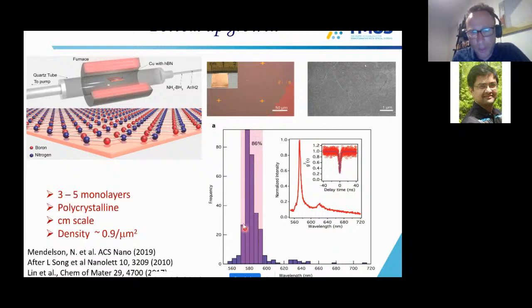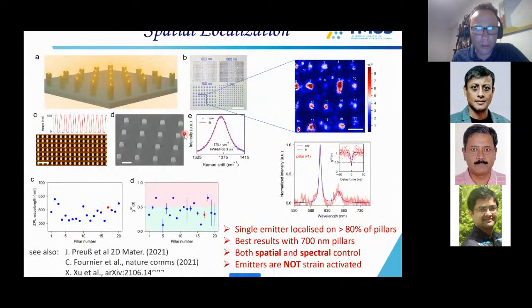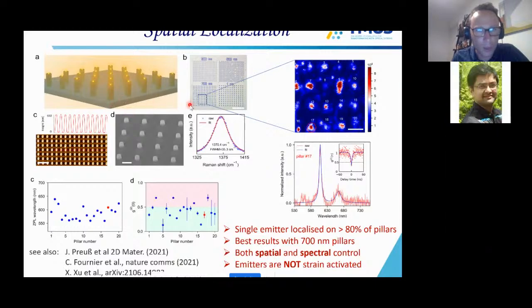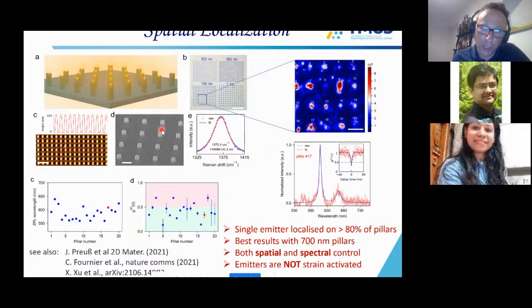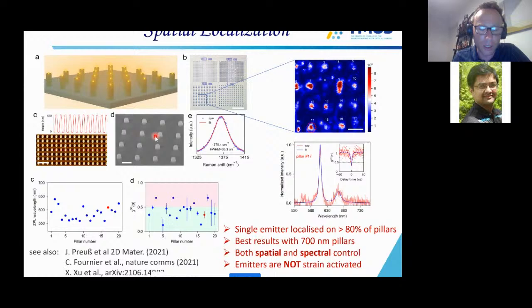So this is a spectral control, so we can now engineer them at the right spectral position. And to achieve also lateral control, you can then grow them on pillars. Here I just want to emphasize straight away that we are growing directly on the dielectric pillars. This is silicon oxide. And this is important not only because you can achieve spatial localization, but you can also then try to grow in actual photonic devices. So for example, if you make a photonic crystal cavity or a microring or microdisc cavity, you can then grow your hBN directly on top.